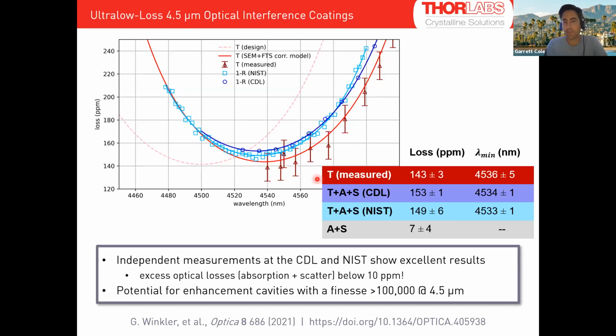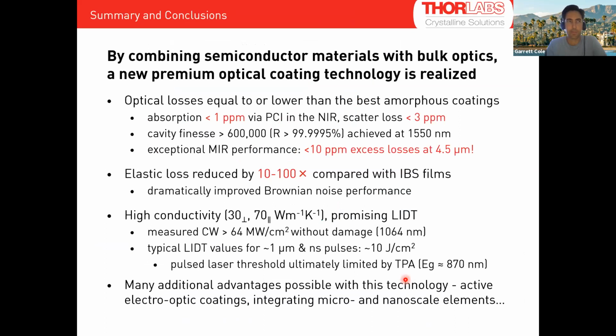But there's now the chance, if we bring the transmission down, that we could do enhancement cavities with a finesse well over 100,000 in the mid-IR. Current record finesse values at this wavelength range are at the 20, 30,000 kind of level. So now we'd be able to exceed 100,000 with our low absorption optics.